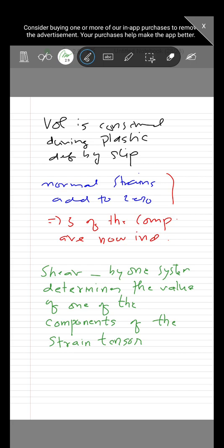So five independent slip systems are needed to produce an arbitrary change in shape. These are the five systems that von Mises has talked about. Now in polycrystalline materials, if a grain is not free to change its shape, strain incompatibilities which develop at the boundaries with other grains would produce high local stress and fracture. So this is an important point.